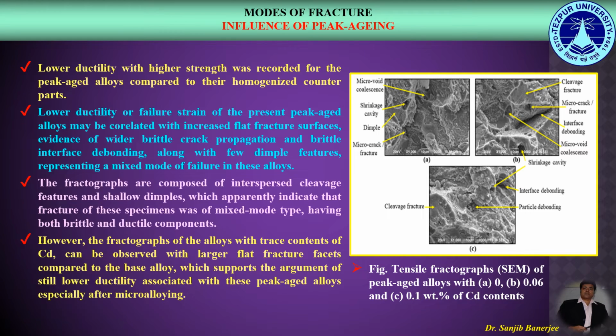To study the influence of peak aging, we can see in this figure the tensile fractographs of peak aged alloys with 0, 0.06 and 0.1 weight percent of cadmium. Now lower ductility with higher strength was recorded for the peak aged alloys compared to the homogenized alloys. Such lower ductility was correlated with the increased flat fracture surfaces, as we can see in these figures, evidence of wider brittle crack propagation and brittle interface debonding, along with few dimple features representing an overall mixed mode of failure. However, the fractographs of the alloys with trace contents of cadmium, that is in figure B and C, can be observed with larger flat fracture facets compared to the base alloy, which support the argument of still lower ductility associated with these peak aged alloys, especially after microalloying.